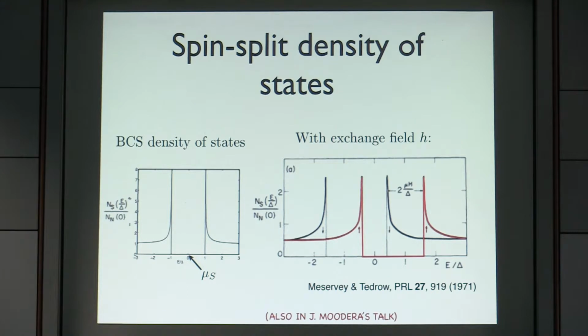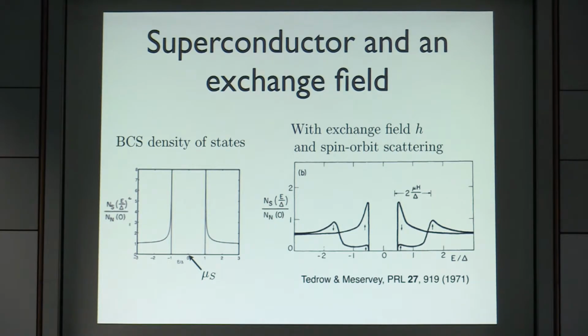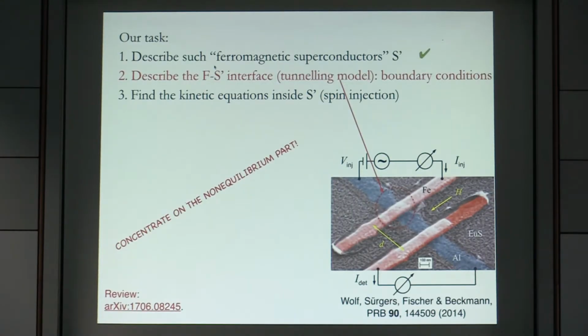Now you can also study what happens to the density of states. This is 1970s physics. This is the BCS density of states without an exchange field. If you add an exchange field, without spin relaxation, you just get two shifted copies of this density of states: for spin up you shift to the right, and for spin down you shift to the left. This was measured by Meservey and Tedrow in the 1970s. If you add spin relaxation, these peaks broaden a little, and with very strong spin relaxation you get rid of the double peak feature, and depending on whether it's spin-orbit or spin-flip, you either kill superconductivity or just come back to the spinless situation. So this was the first task, 1960s and 70s physics.